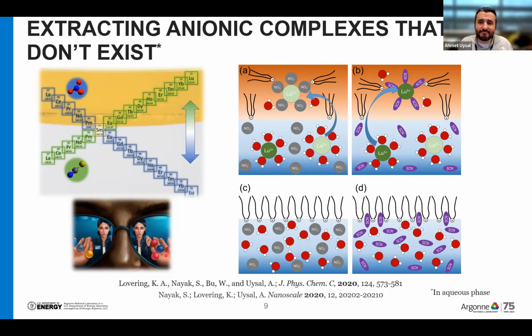And this is completely challenging to our typical specific ion effects understandings, because in specific ion effects, typically what you have is, as you go down the Hofmeister series, you get more adsorption, less adsorption. There are quantitative differences between the behavior of the anions, especially thiocyanate and nitrate. They are closer to each other in the Hofmeister series. You really don't expect a complete reversal in the trend. And that is what is very nice about solvent extraction. It is such an interesting system. It cannot be described with one thing only. It is not a simple adsorption process.